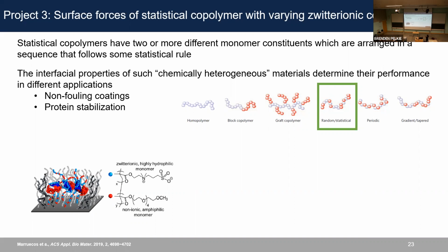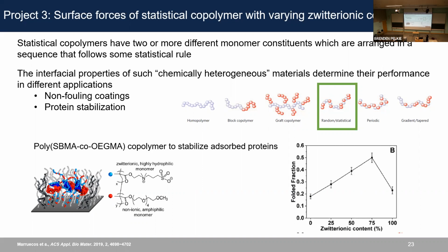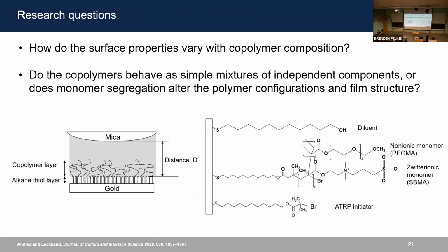The biggest motivation for that is that statistical copolymers are great for preparing chemically heterogeneous materials. For example, in this work done by Dan Schwartz's group, a sulfobetaine and oligoethylene methacrylate based statistical copolymer was used to stabilize fibronectin. And it was shown that at an intermediate zwitterionic content, the most stability of the protein was achieved. And so we wanted to follow up on that.